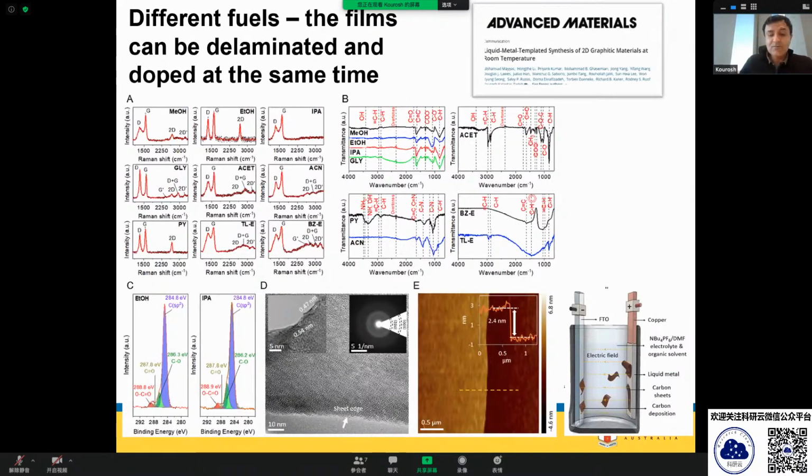But what we wanted was to obtain smooth graphitic material. Instead of letting the liquid metal move around, we painted liquid metal on the surface of an electrode, here the surface of copper. We apply the voltage across. It is produced on the surface. The surface is not deformed, and because of self-exfoliation, it exfoliates and goes to the other electrode using electrophoresis. As I say, the surface is smooth. You can make it multiple layers by increasing the voltage. And the interesting thing is you can have relatively highly crystalline graphene oxide.